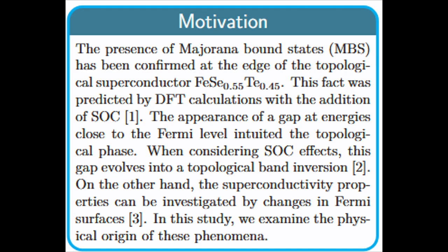The presence of Majorana bound states has been confirmed in the topological superconductor iron, selenium sub 0.55, tellurium sub 0.45. This fact was predicted by DFT calculations with the addition of spin-orbit coupling effects. The appearance of a gap at energies close to the Fermi level is intuited by the topological phase. When considering spin-orbit coupling effects, this gap evolves into a topological band inversion. On the other hand, the superconductivity properties can be investigated by change in Fermi surfaces. In this study, we examine the physical origin of this phenomenon.